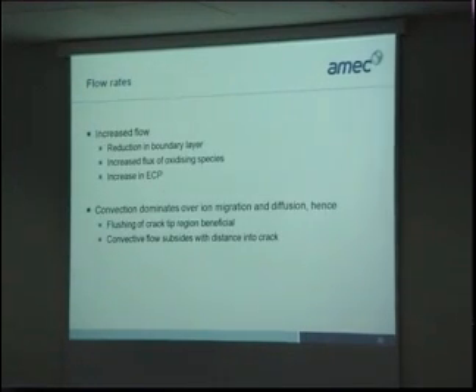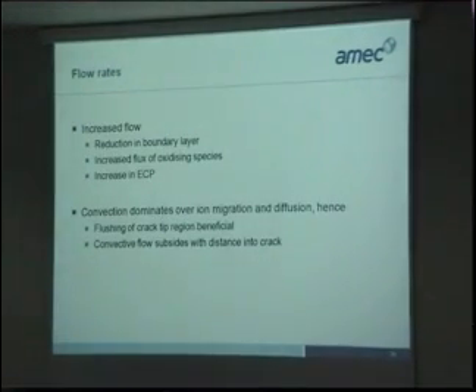Flow rate effects were important. In fact, if you increase the flow in a region, bearing in mind that we're not just talking about the main vessel, we're talking about all different parts of the vessel and components, you get a reduction in boundary layer with increased flow, which means an increased flux of oxidizing species, and this results in an increase in the electrochemical potential. But convection dominates over ion migration diffusion, and so although the flushing of a crack tip is beneficial, the convective flow subsides as you disappear into a crack.